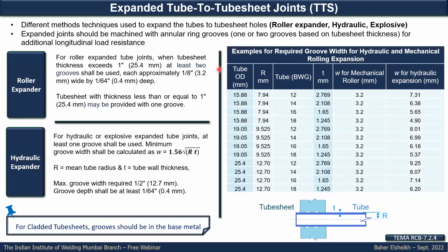The three different techniques normally used in the expansion are roller expansion, hydraulic expansion, and explosive expansion. Normally, when we need to apply the expansion, you should have annular ring grooves. The most common is to have two grooves as per the TEMA requirement, but there is some exception: in case you have a thin tube sheet, whose thickness is less than 1 inch, you can apply only one groove.